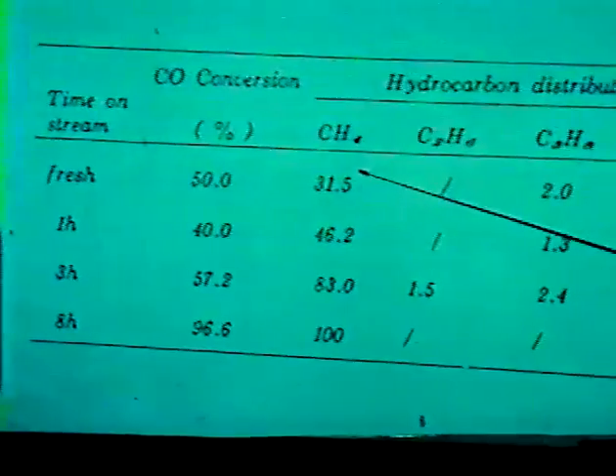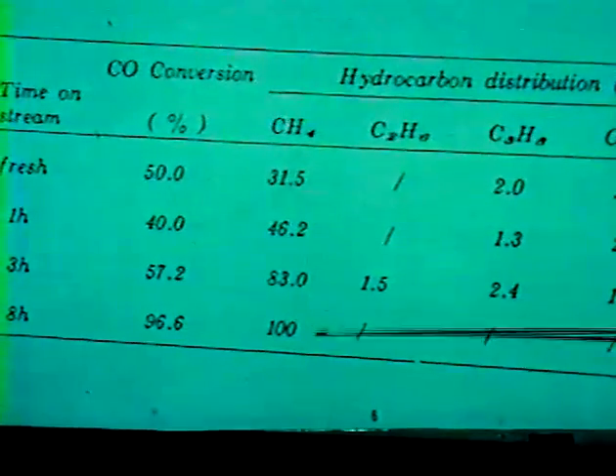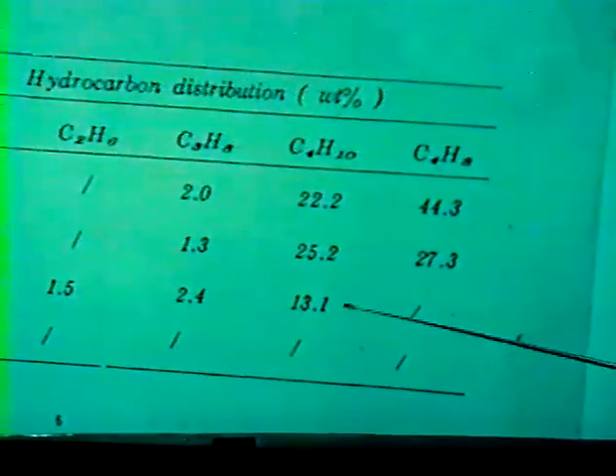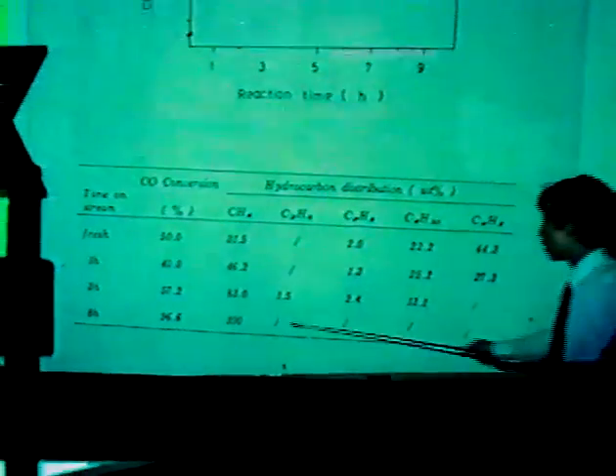With increasing reaction time, the CO conversion decreased at first, then increased, and finally reached a steady state. It is interesting that the selectivity to methane increased with the reaction time, while the selectivity to higher hydrocarbons decreased. After reaching the steady state, the product was only methane.